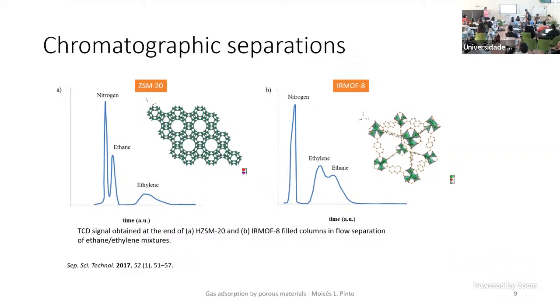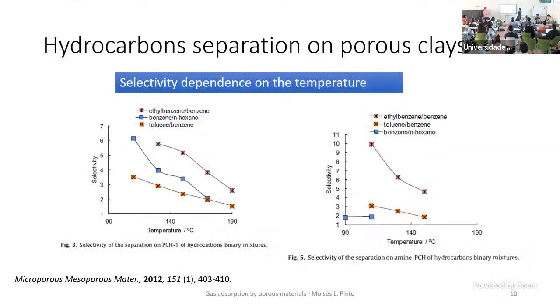Imagine that you can perform these experiments at different temperatures, and then you can calculate the selectivity as a function of temperature. So we have selectivity here, and temperature here, and in this case, just to highlight that you can do this type of thing for different mixtures, like in here, ethylbenzene, benzene, and hexane, and then toluene, benzene, for different types of materials. And of course, this is from the point of view of a possible separation application.